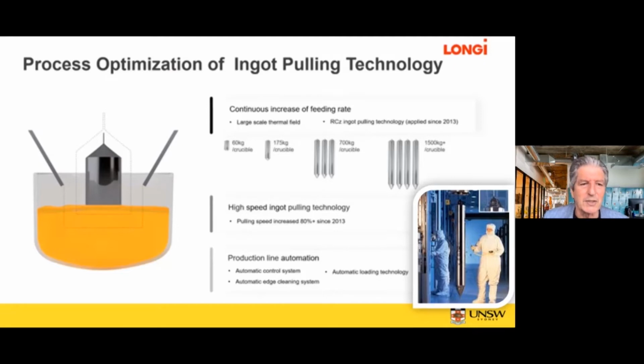So these containers that the silicon is melted in prior to the crystal growth have to be very pure, otherwise the impurities from the container work their way into the silicon, and you don't end up with the quality that you desire. And they're quite expensive because they're pure. But by recharging those crucibles during the growth process, you can use the crucible multiple times, so that you save on costs that way. So the photovoltaic industry has gone to the growth of multiple large ingots from the one